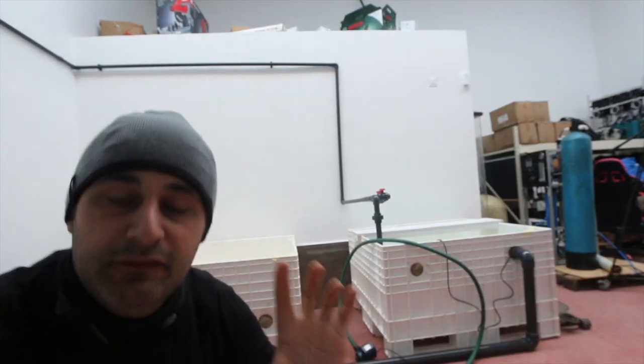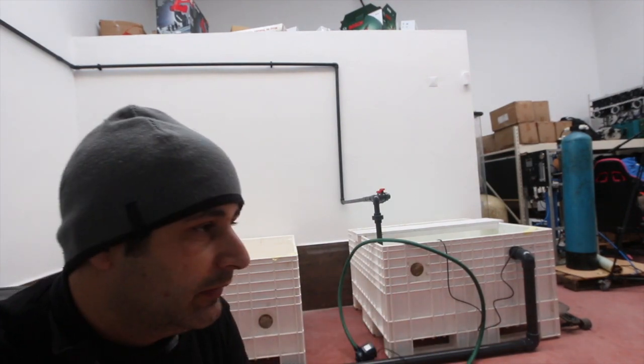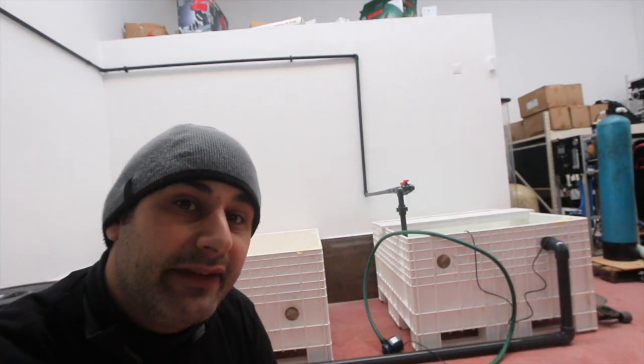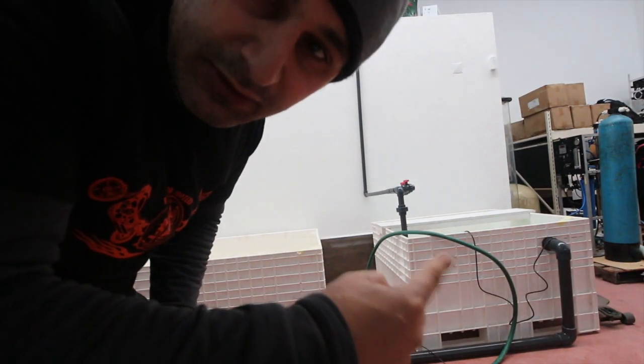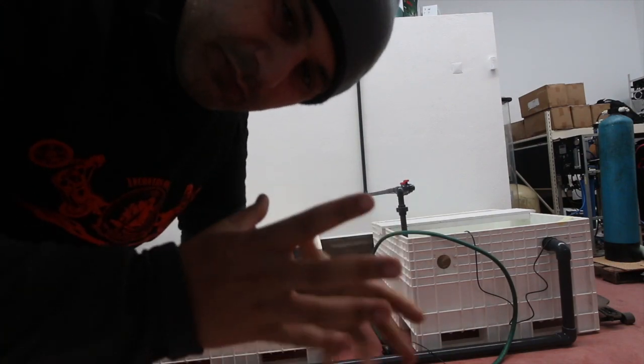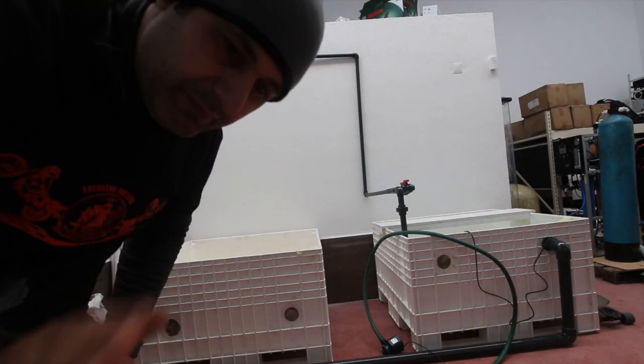The thing is, fiberglass is actually a pretty cool material, but you gotta sand the surface and then use some cleaner, like a PVC cleaner or acetone, I think that's the way you say it, and that will clean it, and then you apply the fiberglass. And if it's a big hole like this, you want to have another little circle, so it kind of gives it like a mold, so it will stay there and not move too much. And if you use Teflon tape, the fiberglass doesn't attach to Teflon tape. So those are some of the basics.